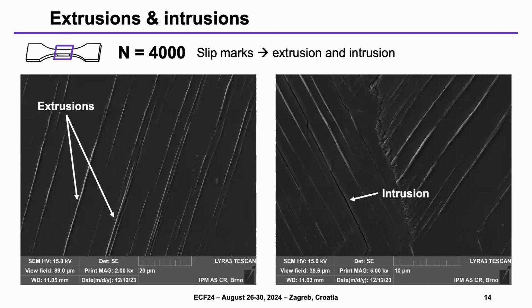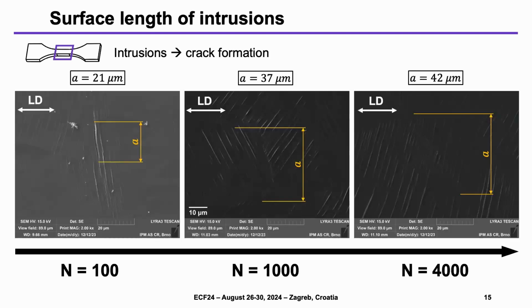In this case, we measure the surface length of some of these intrusions, because using SEM it is impossible to measure the depth of the intrusions. So here I reported the value. The surface length ranges from 20 to 40 microns with increasing the number of cycles.